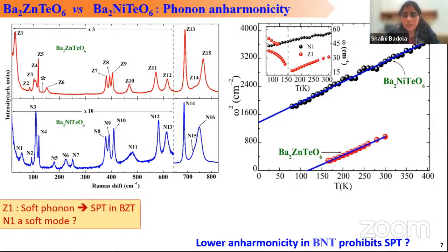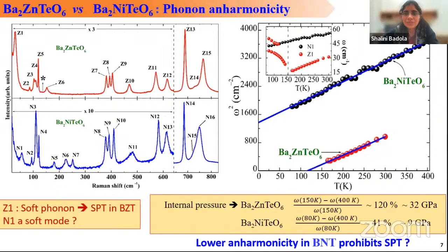Okay. So this suggests that this N1 is not a soft mode driving the phase transition in case of BNT. And therefore, to compare the anharmonicity, we have estimated the anharmonicity in case of the nickel system, which is around 41%. If we compare with the zinc system, where it is around 120%, it is 3 times lesser than the zinc system. So this gives an indication why there is absence of phase transition in case of BNT.